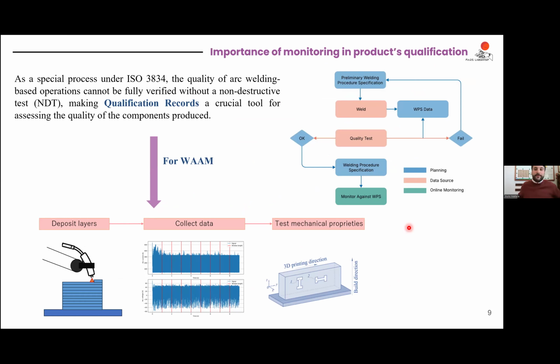Now, why is this important from a certification perspective? Because if you have a look at the qualification procedure for welding processes, but it's the same for any kind of additive manufacturing process that is a special process under ISO standard, you need to weld or deposit, collect data, and test the mechanical properties and inspect the microstructure to inspect potential defects inside the part. And then if everything is working, you are going to qualify this parameter.